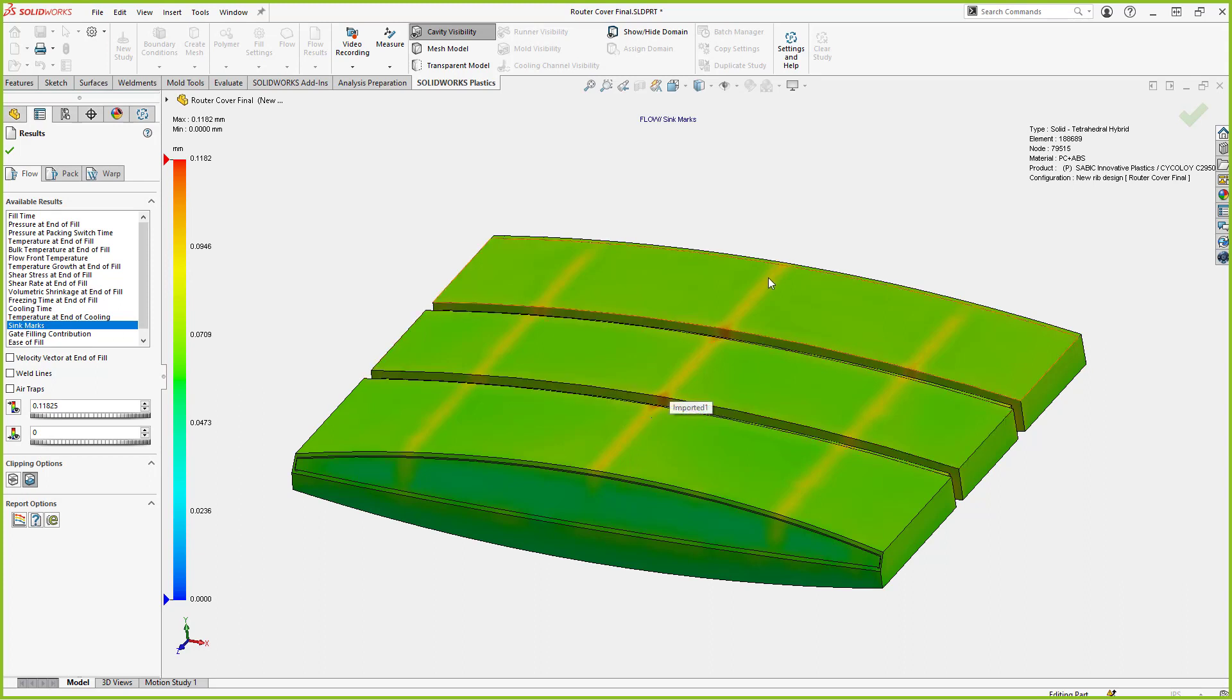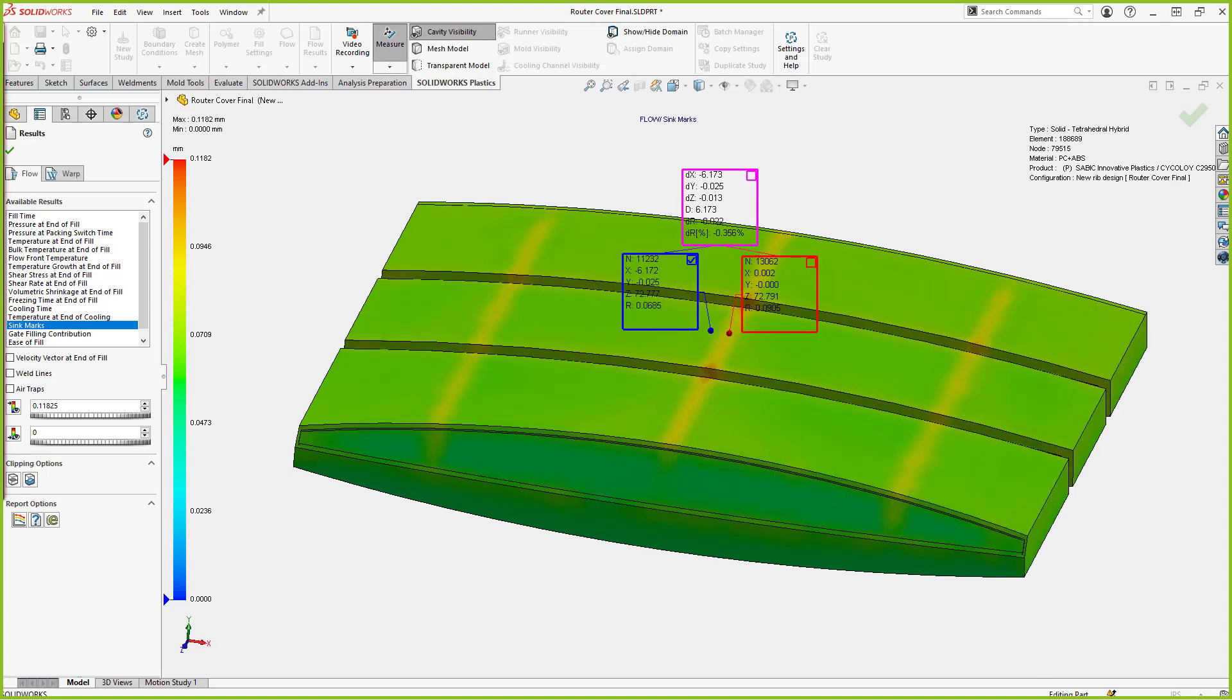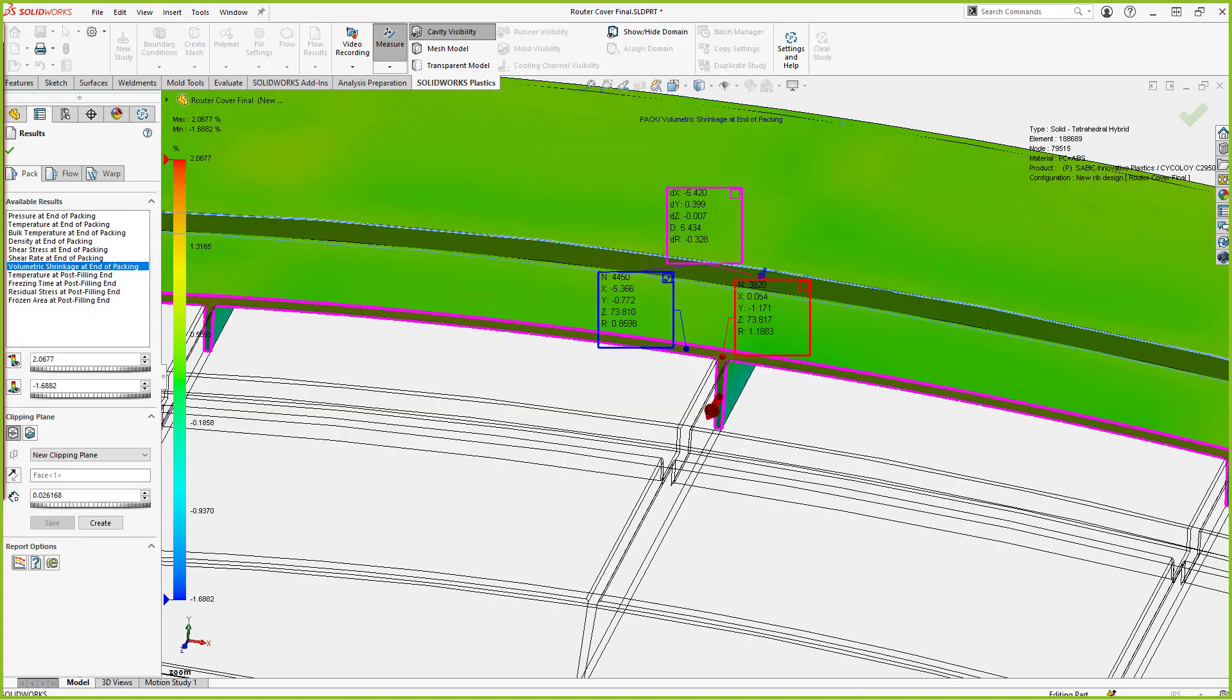And then we can look at sink marks. So we've got different sink mark profile on this. We've got less sink marks in the areas of the ribs that we were looking at. Using the measure tool again, our resultant difference now with the new rib design, with the measuring in the same point, we've actually changed our resulting difference. So we've actually got a whole lot less sink mark in this area. I can also look at the volumetric shrinkage of it now. And the difference in my volumetric shrinkage in those areas is less than it was in either one of the previous two analyses. So we've reduced that, but we did not have to increase the packing.